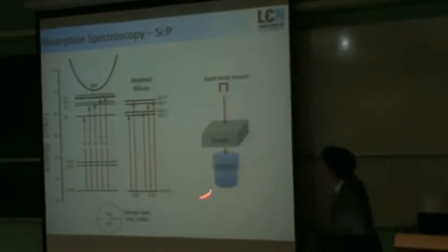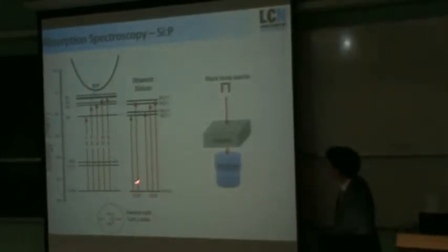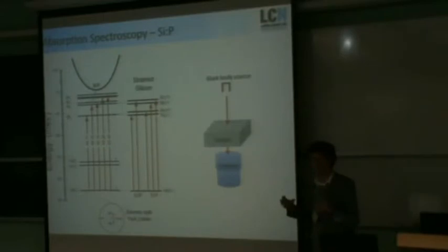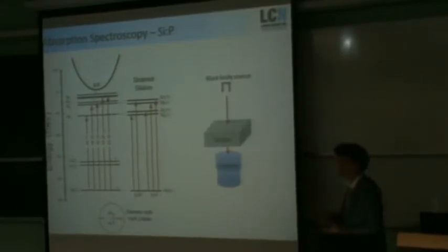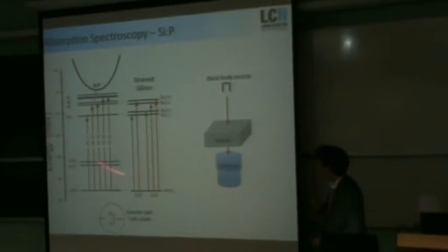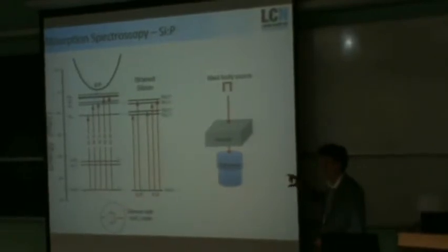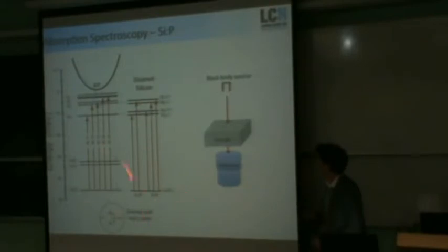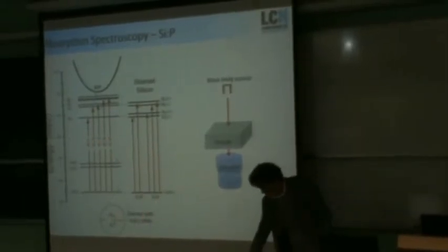Another important note about this kind of measurement is that if there's any kind of strain inside the silicon device, that perturbs these excited states and changes their energy here. Another important note is that the actual energy level that we're talking about is much greater than that used in Zeeman splitting, when you're talking about the individual energy of spin states in an atom. So really these are quite large energies in the sample.